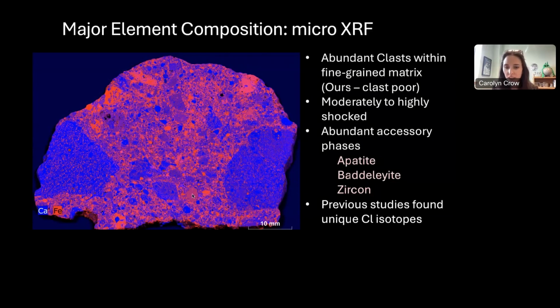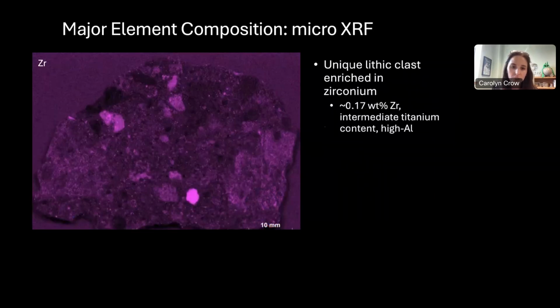But there's one of particular interest, which is right down here. It doesn't necessarily stick out in this elemental map, but when you look at zirconium, this is the zirconium map of this sample. You can already see just looking at the zirconium map that this is a very zirconium-rich sample. And this clast is basically 0.2 weight percent zirconium, which got us really excited because we were like, hey, if it is 0.2 weight percent zirconium, there must be a ton of zircons and baddeleyites in there to date. Unfortunately, we were disappointed that there isn't really anything to date in this sample.